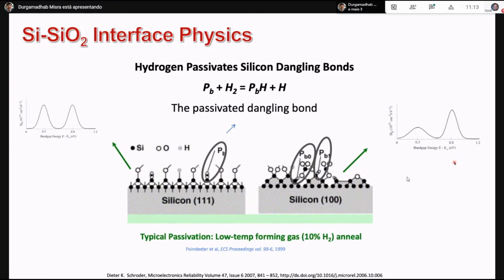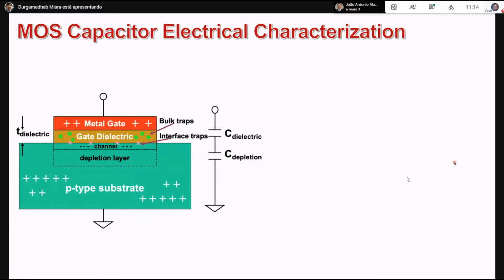Actually, the exposed bonds, which were creating a lot of trouble with the electron mobility and hole mobility in the channel, were resolved by passivation with low temperature forming gas and hydrogen anneal, because hydrogen can passivate those bonds. So this was solved, but the other problem is to find the defects, find the problems in the dielectric.